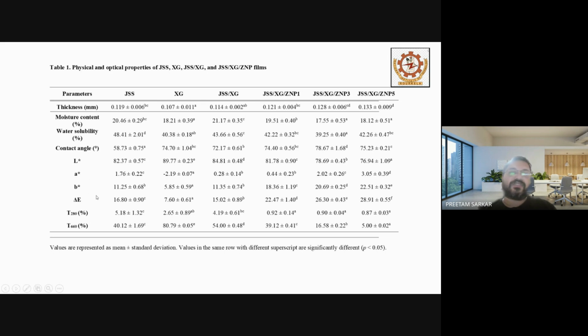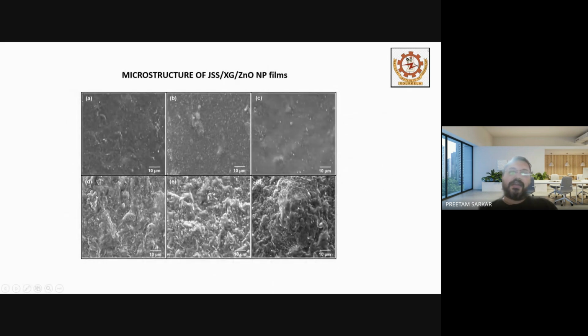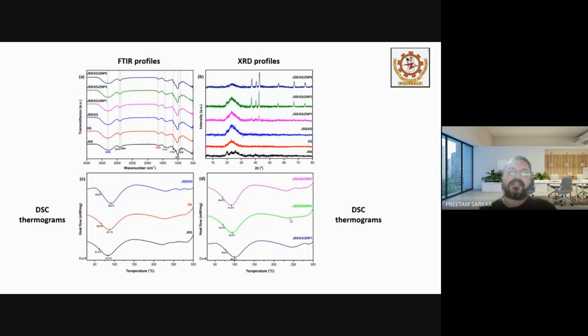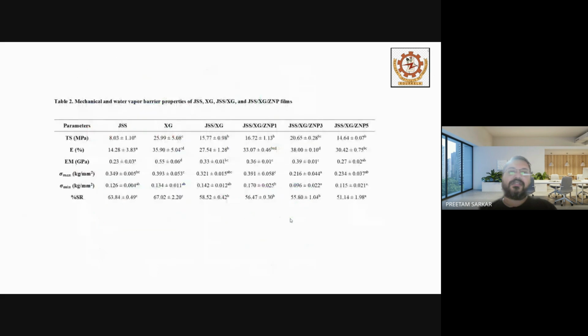And the color parameters. The microstructure, we have done the FESEM. You can see really coarse and grainy structures because of the addition of zinc oxide nanoparticles at the highest level. Then our FTIR, XRD, and DSC thermograms. And these are our mechanical properties. Starting from 8 megapascal, it increases to around 20.65 megapascal. So we can improve the mechanical property of the films with the addition of the zinc oxide nanoparticles.